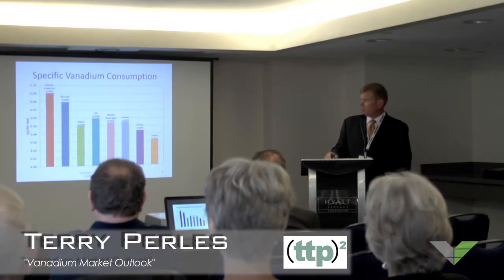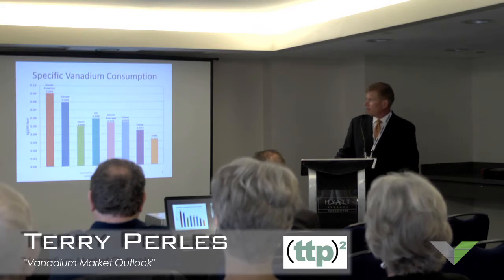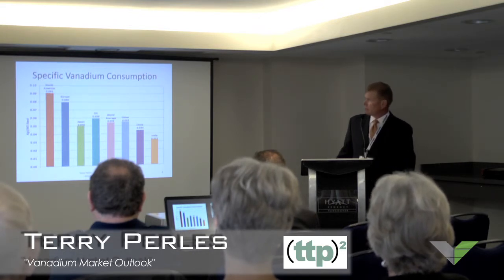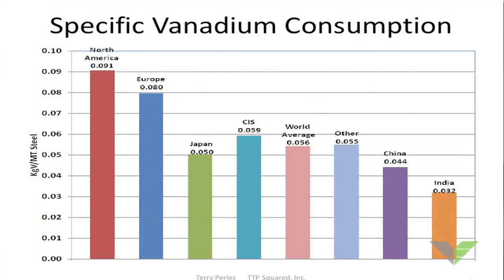Specific vanadium consumption rate varies country by country. Here's the data that shows you that in North America we consume on average just about 0.09 kilos of vanadium per ton of steel. The world average is about 0.056 kilos of V per ton of steel. And if you remember, I said a typical HSLA steel has about a half a kilo per ton of steel. So you see the global average is only about 10% of the actual consumption of vanadium high-strength steel.